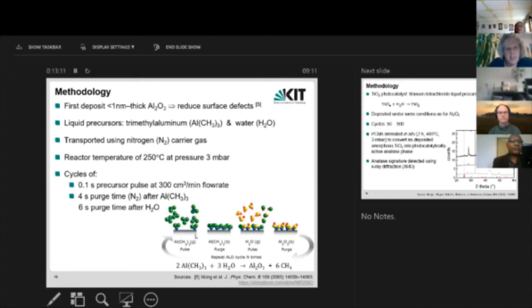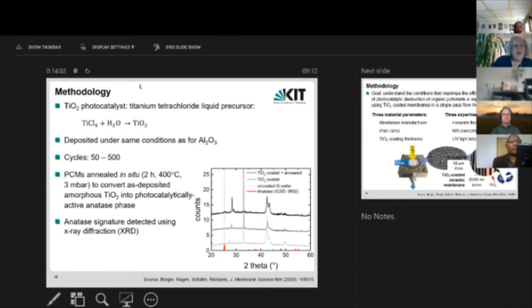And then what you're doing with ALD is this typical cycle that I've shown in the bottom right-hand corner. So you have a very short pulse of your precursor. Here it's only 0.1 second long. Then you have a purge time, which allows the purging of the gases from the system. And then you introduce your other precursor, in this case, water. And then on the substrate, you have the water molecule going in, finding the trimethyl aluminium molecules on the surface, and then a reaction taking place. And then byproducts, which are in this case mostly methane, shown by the equation at the bottom, being given off. And you're repeating this up to hundreds of times to get appreciably thick films. So that's the principle of ALD.